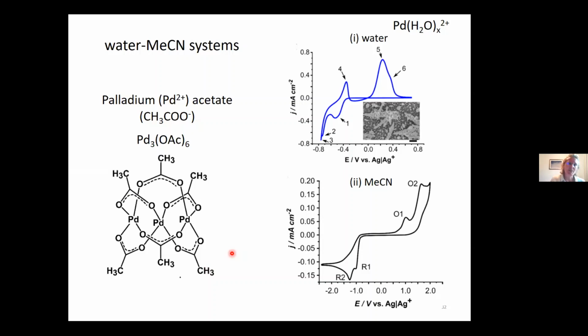Now, when you take the palladium acetate and you take a water system, we can do the CV, and all of this is done on boron doped diamond, okay? You do the CV of palladium reduction in a water-based system, you see palladium electrodeposition, and you can see palladium oxidation behavior as well. And when you go and look under a scanning electron microscope, you can see the formation of palladium particles, palladium structures.